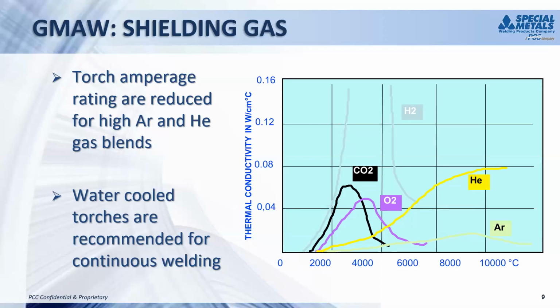But the thing to remember when using these gas blends is your heat capacity for that gas goes down. And a lot of these torches are rated based on CO2 shielding gas. So if you notice on the graph, the CO2 can absorb a lot larger amounts of heat than, say, typical argon or even argon helium blends. So if you've got a torch that may be rated for 300 amps with CO2, you really may only be able to use that torch continuously around the 150 to 170 amp range for a nickel alloy if you're running that argon shielding gas.